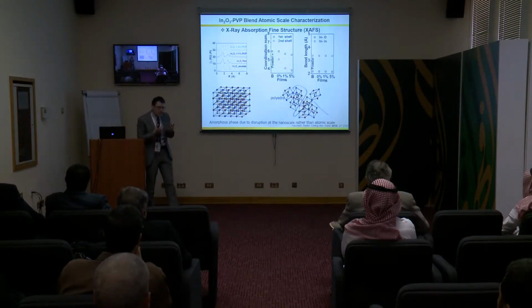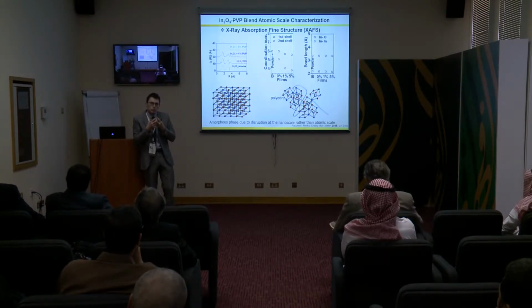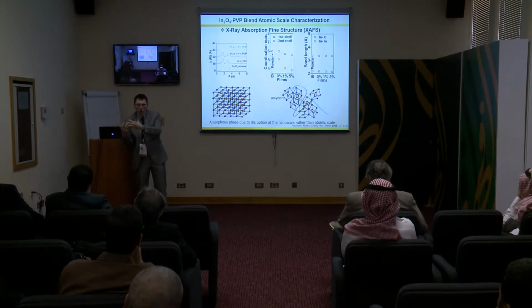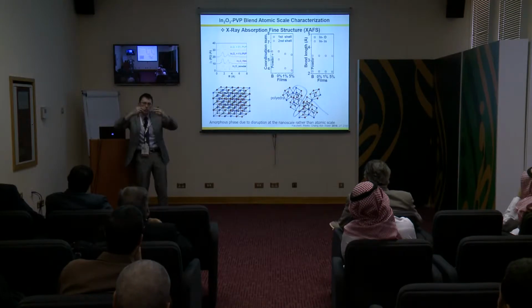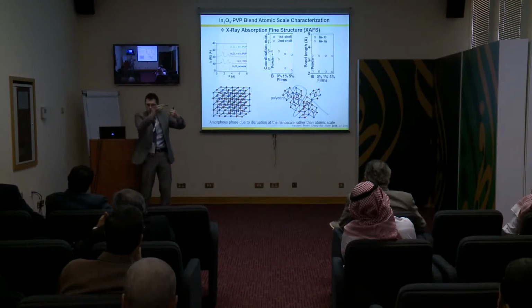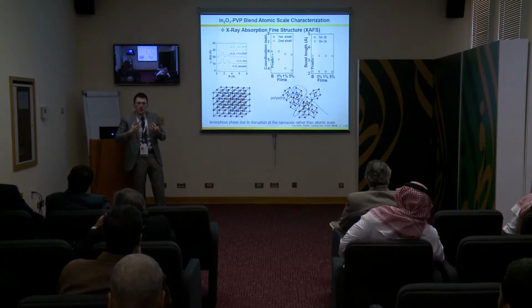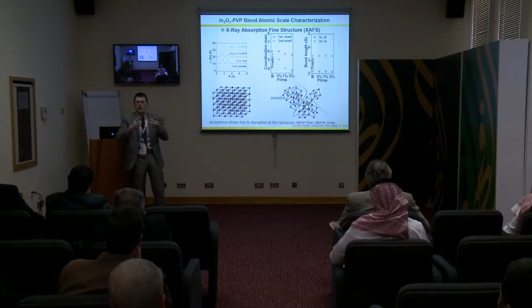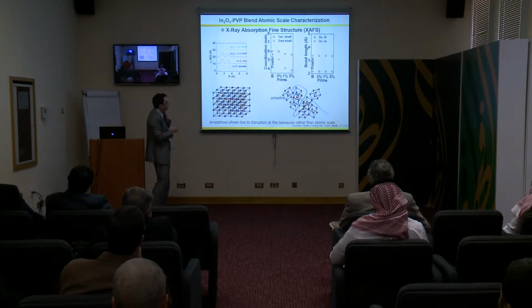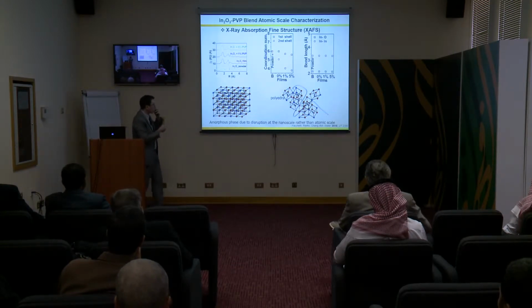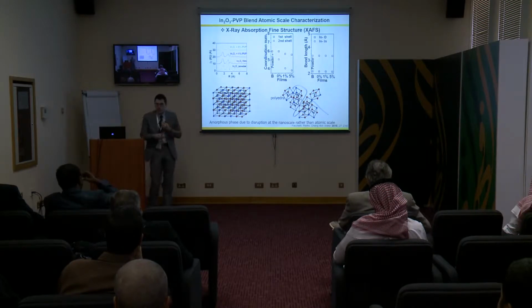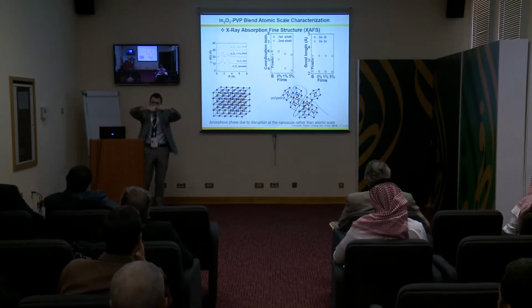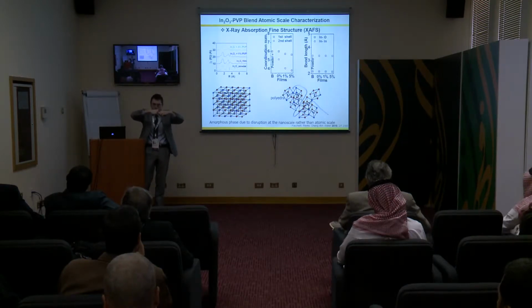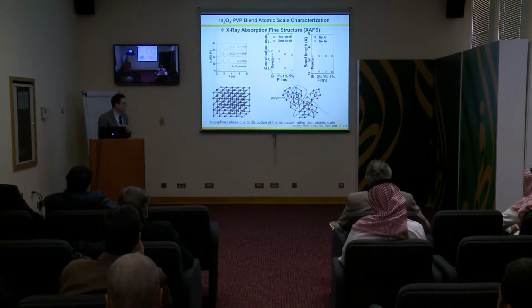We try really to understand at the molecular scale, so what does this polymer do? Because you can think about, you can form a solid solution, or in metal oxide you have typically these octahedra which are connected, and having a good connectivity is where the electron then can move through, okay? So if you want to have a material which can remain a semiconductor, it means these octahedra have to somehow remain connected upon doping with the polymer. And this experiment using X-ray absorption fine structure tells us that we do disrupt the lattice of the matrix to some extent, but these octahedra remain connected, and we can really see by looking at this coordination number, this coordination length of the second sphere. So we still have these octahedra which mostly through the edge remain connected, which is essential to have some degree of transport.